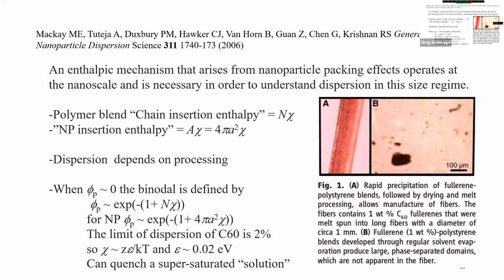So in his case, I mean, he makes a point of talking about this. So he says the only way to get this to go into a single phase for the C60, first, you can only go to 2% C60. If you go above that, it phase separates. And the only way to get it to go in is you put it into a solution, whatever solvent he uses, but then from that, he spins fibers out of it to quench it immediately. Like the solvent goes away right off, and he locks it into that structure, right? So that's how he makes his miscible systems. You know, it's a totally kinetic process.